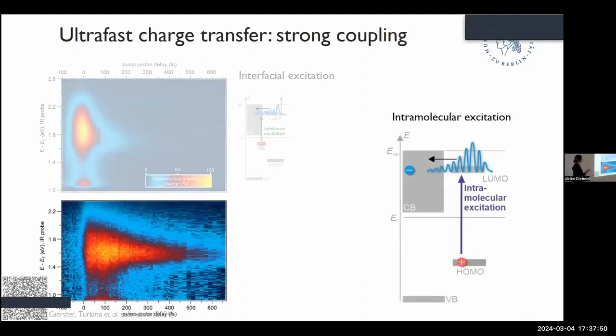When we now do the intramolecular excitation, it's the same time axis as above. You can see that the dynamics are longer. It takes longer for the population to decay. This means charge transfer is slowed down. And what is the reason? Well, the reason must be the position of the hole. And we interpret this as the Coulomb potential here constricting the wave function more to the molecular region, so reducing the wave function overlap and therefore the probability of the electron to transfer.